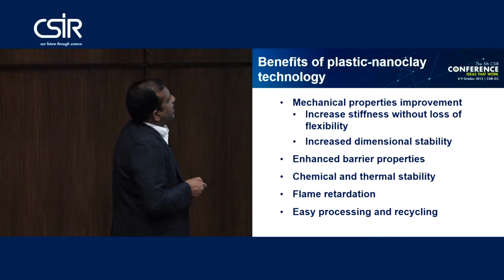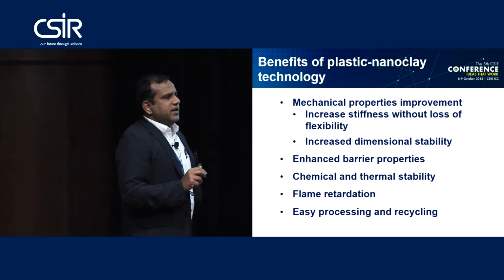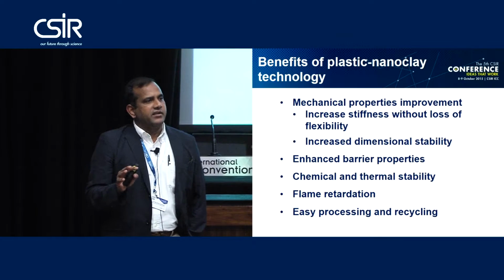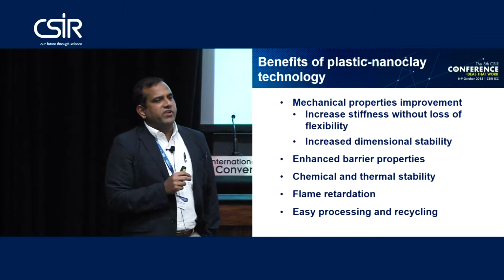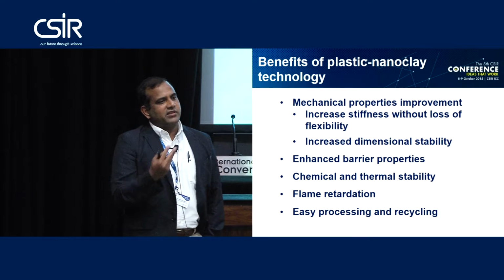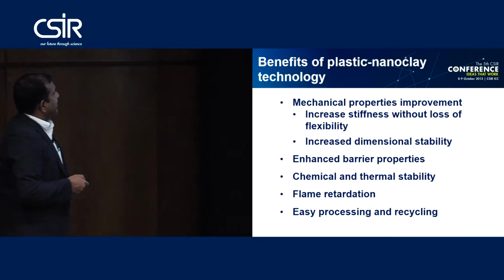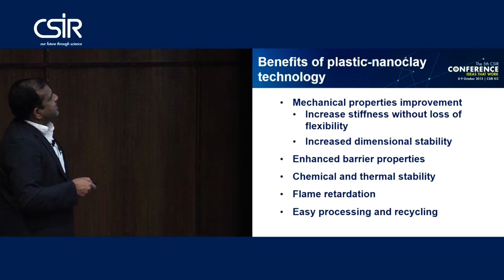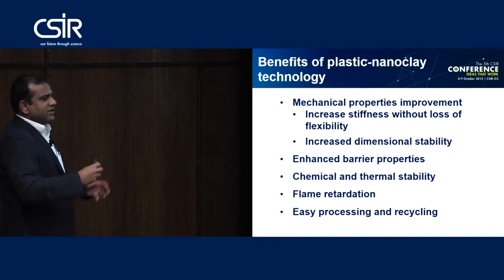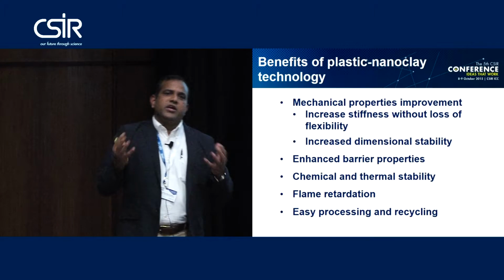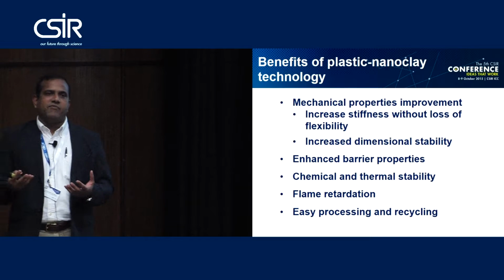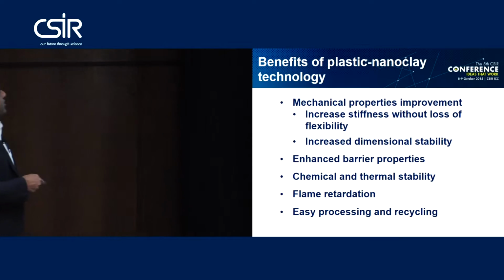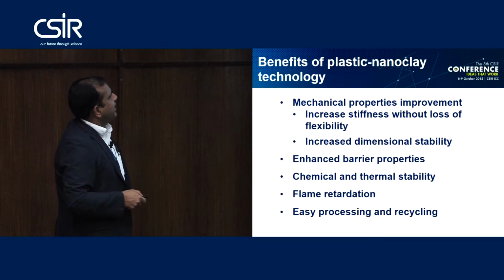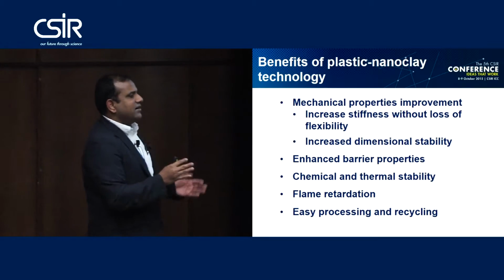You can increase the stiffness without loss of flexibility. That is the most important part, because for those working on composites, the general understanding is that if you incorporate a foreign material inside a matrix, you immediately lose the ductility of the matrix, because you make the matrix less ductile. And at the same time, you have increased dimensional stability. Also for nanoclay platelets, because of the platelet type of orientation or geometry, if you disperse the nanoplatelets inside the polymer matrix, you can have improved barrier properties, and that is what we are looking for in packaging applications. Then chemical and thermal stability, you can also improve the flame retardant behavior of the polymer matrix, and you can have much better flowability because of the clay platelet-like structure.